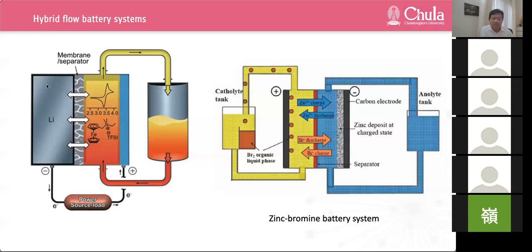An example of this system is the zinc bromine flow battery, where the system uses zinc as solid electrode and uses bromine, which is liquid, at the other electrode. When the system is being charged, zinc metal is plated on the anode side of a carbon-based electrode. Meanwhile, bromide ions are oxidized to bromine at the positive electrode. And during discharge, the reverse process occurs. And this system has a high cell voltage and energy density, and the expectation is that low-cost materials can be used.